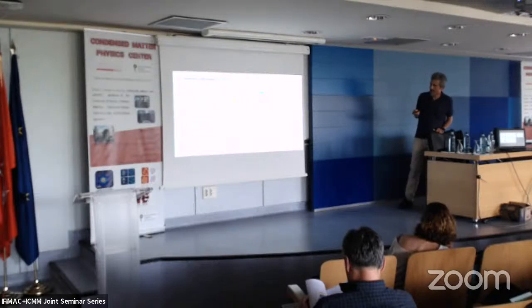To measure, we need to use several different frequencies because we want to measure many things at the same time. Here, for example, we want to measure the average temperature of the wire, so the changes in resistance will give us the average temperature of the wire. We measure also the temperature of the tip by the thermoelectric thermocouple that we have there. And we also measure the tunneling current going to the substrate. So we can use it as an STM.